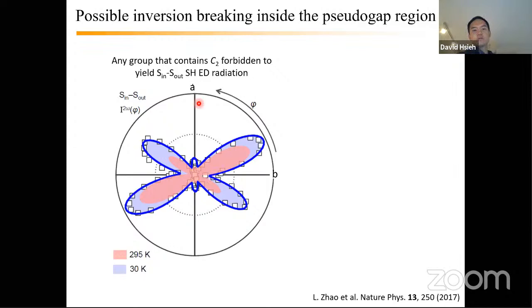Now, just by symmetry, one knows that in this SS channel, the second harmonic generation in the electric dipole radiation channel is forbidden if the system contains C2, okay? And so if the symmetry breaking below T star were occurring because of a transition to another order with C2 symmetry, then you really shouldn't see any radiation in the SS channel, at least in the electric dipole approximation, okay?